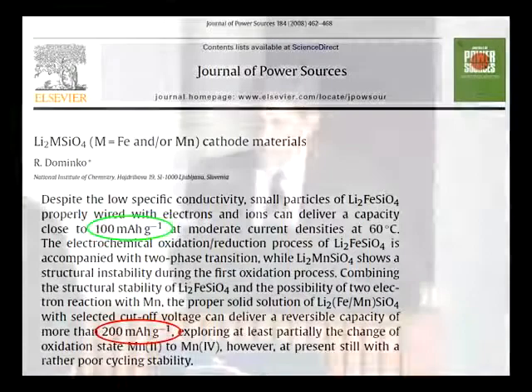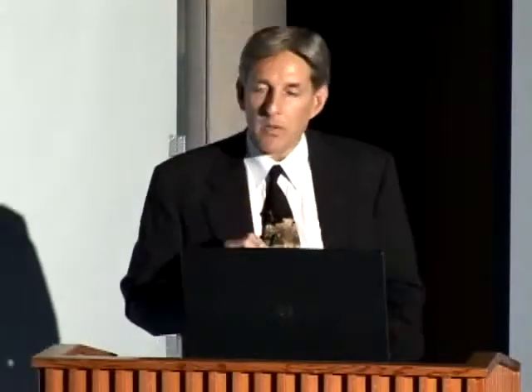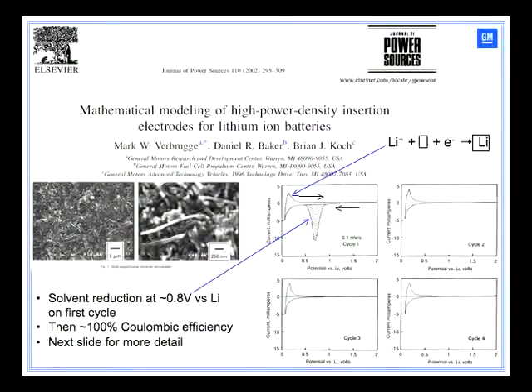I want to speak a little bit about life and get into some durability issues. There are two problems that give rise to life issues in lithium-ion batteries: chemical degradation and mechanical degradation. Chemical degradation affects calendar life — just letting a cell sit there, especially heated up, will cause it to chemically degrade. Cycling — the expansion and contraction — gives rise to cycle-life problems. The two working together unfortunately give combined problems. We're talking about the wear-out mechanisms in what's conventionally called the bathtub curve. In automotive we typically talk about 10 to 15 years — we have a 10-year warranty on the battery pack in the Volt.